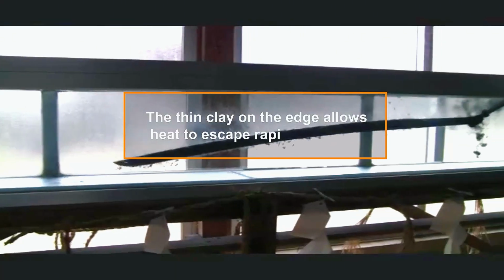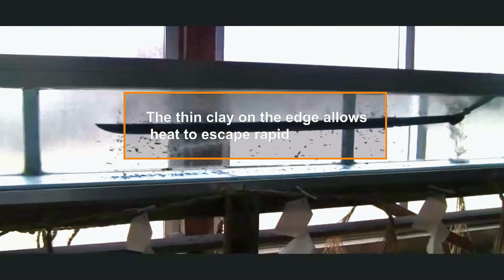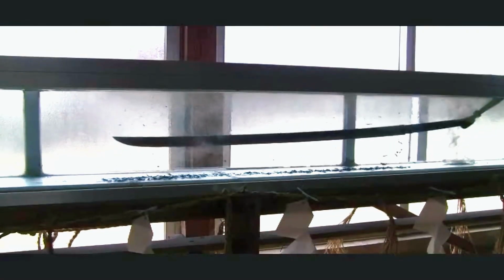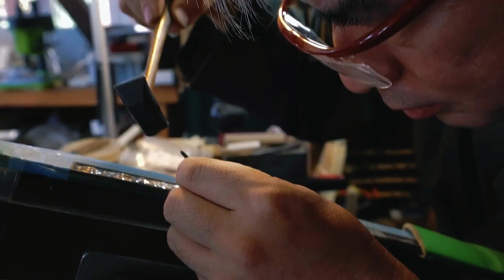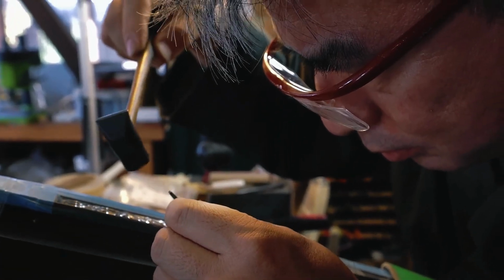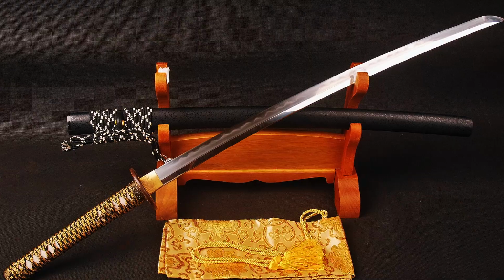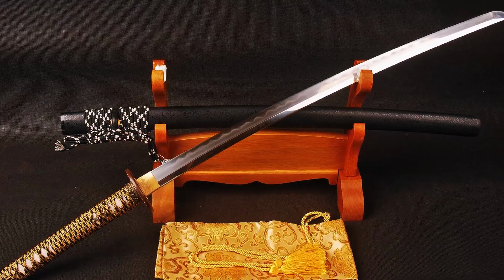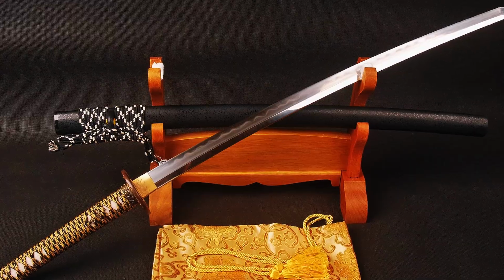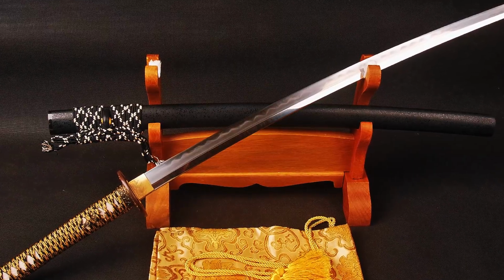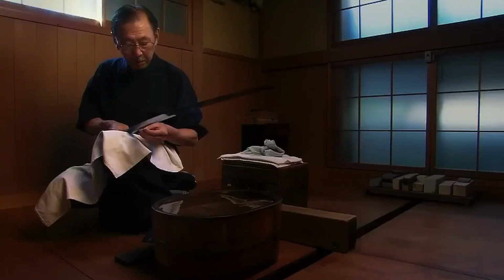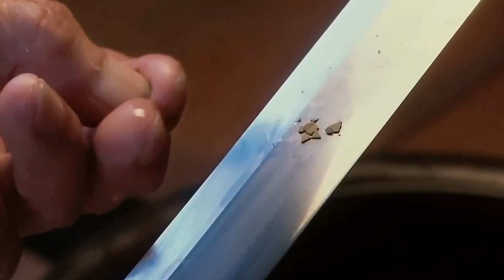The thin clay on the edge allows heat to escape rapidly. Carbon atoms don't have time to move. They get trapped, forcing the crystal structure to change to martensite, one of the hardest forms of steel known. The hardness reaches 60 to 65 on the Rockwell scale. The thick clay on the spine acts as insulation. Heat escapes slowly. The spine forms a softer structure called pearlite, with a hardness around 40 on the Rockwell scale.